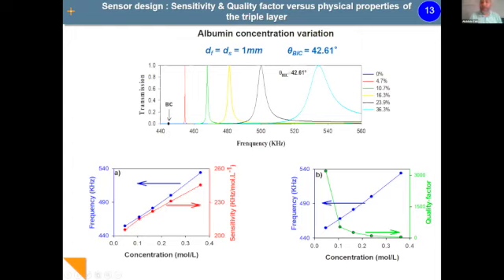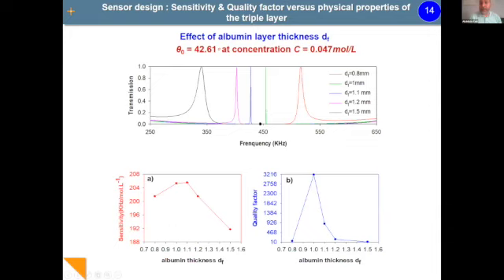In this case, we play on the concentration to move the resonance. We can also play on other parameters. Here we fix the concentration and we play on the thickness of the liquid layers. We can also move the resonance. This means that we can choose the concentration, one operating point, fix this point, and introduce changes of concentration, and we can take advantage of the quality factor near the targeted concentration. The sensitivity remains constant, but this is normal because the resonance is completely localized inside the liquid layers.